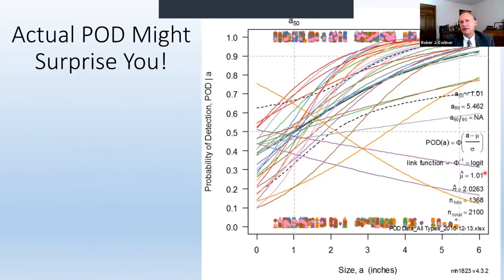In fact, if I plot all the data of the different inspectors on the POD curve, and you may be familiar with these, where the vertical axis is probability of a hit, in other words, finding a crack, and then this is crack length on the horizontal axis, you'll see some interesting trends. In other words, you would expect, as most of the data show, that for individual inspectors, the likelihood of finding the crack increases with crack size.